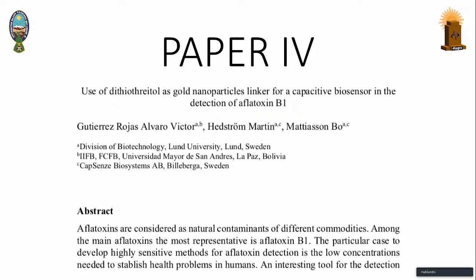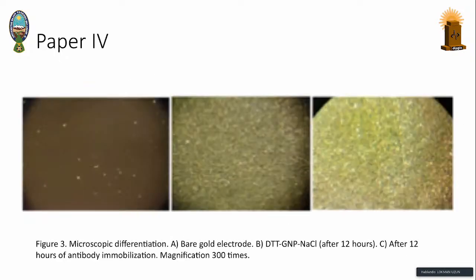In the first study, Alvaro used the antibody and then immobilized it on a gold surface, a linear surface. Now it focused on increasing conductive layers by using gold nanoparticles and immobilizing the recognition element on these nanoparticles, applying the counter-ion effect to form a network formation between these gold nanoparticles on the electrode surface.